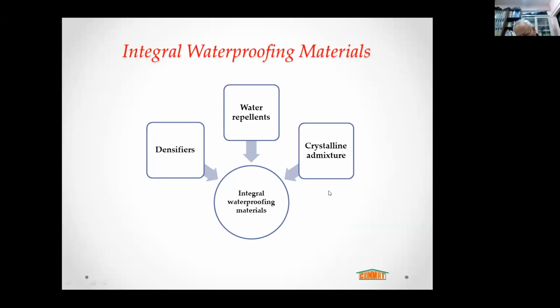The crystalline admixture, yes, is a very significant development in integral waterproofing, where all that you do is you make the material, instead of hydrophobic, hydrophilic, meaning you love water. And in the process, the cement and the proprietary chemicals that you make use of together really grow crystals inside your concrete element, and you try to really block pores and bridge up the cracks. And today, the technology has come to a level where this material can lie dormant in concrete. And if in the later life of the concrete there are cracks, this material can still be brought back to activity, and it bridges up the cracks and continues to keep them sealed.